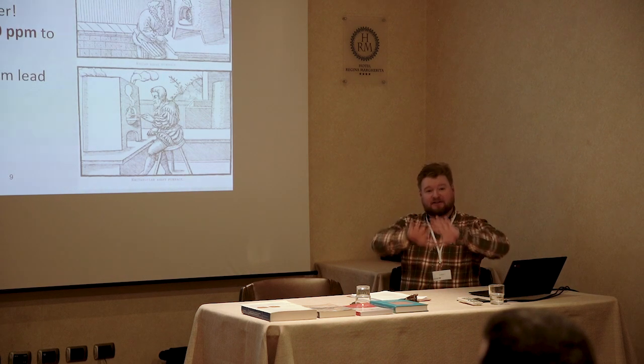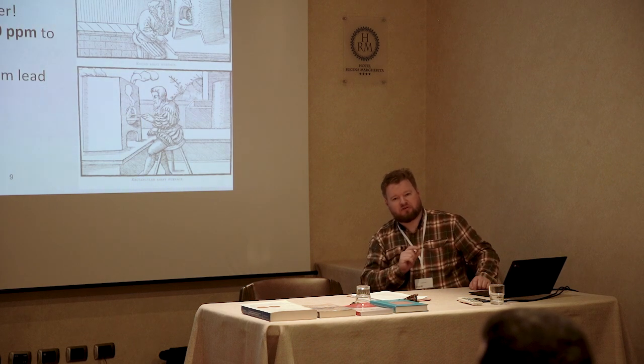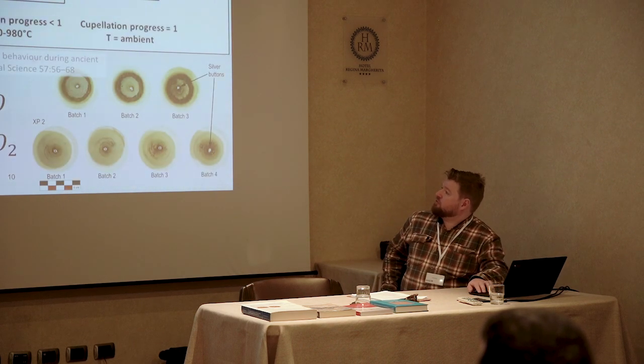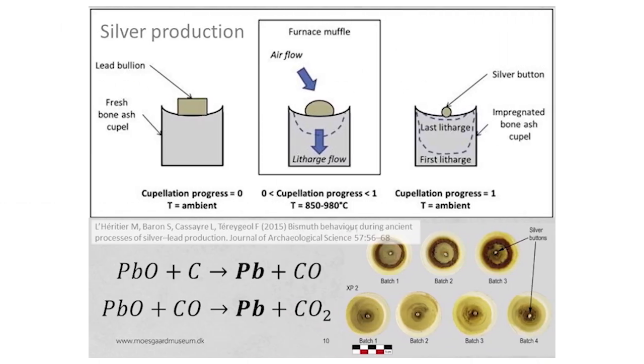And so the lead reacts away, the silver is quite happy on its own, doesn't want to react with anything, so you're left with this small puddle of silver. I've just taken these pictures from a paper published by Maxime, which I think shows nicely how that works. The lead goes into this matrix, and then you're left with your silver pool.